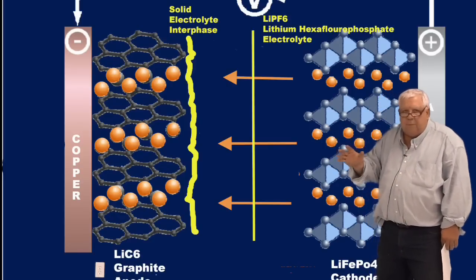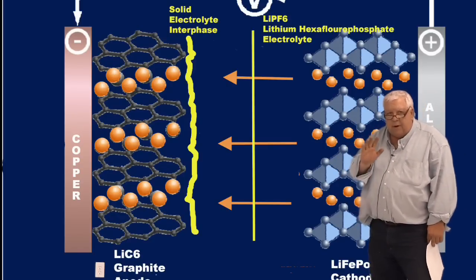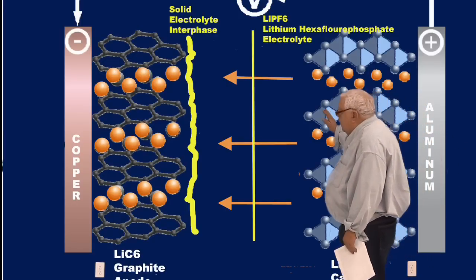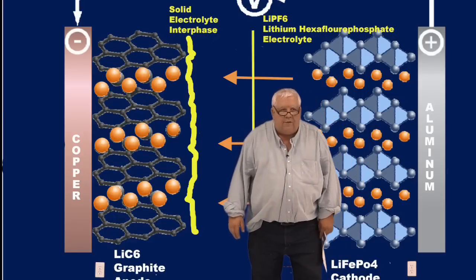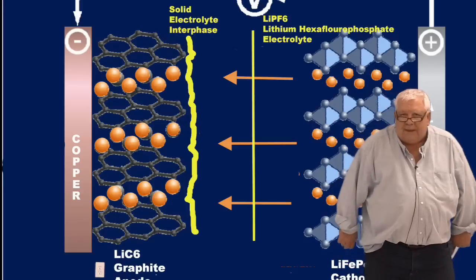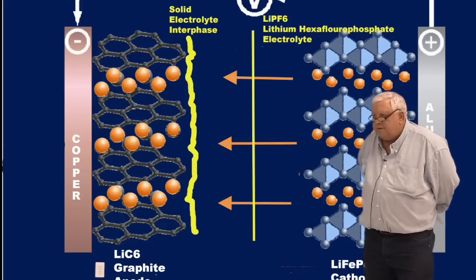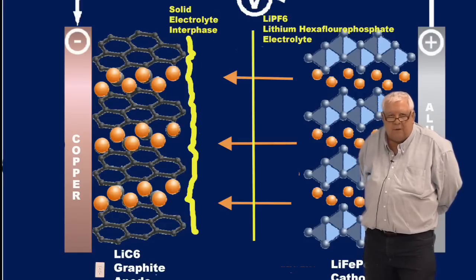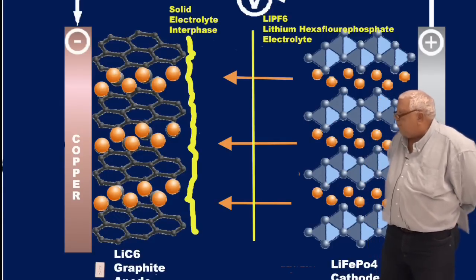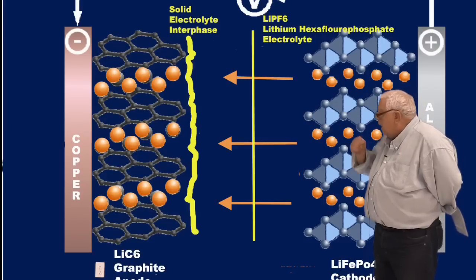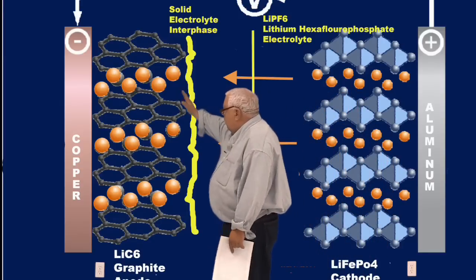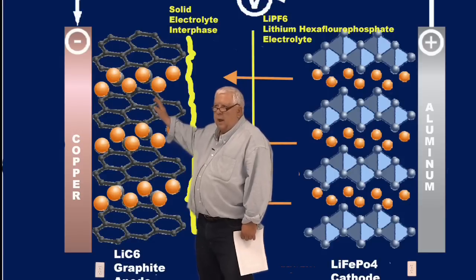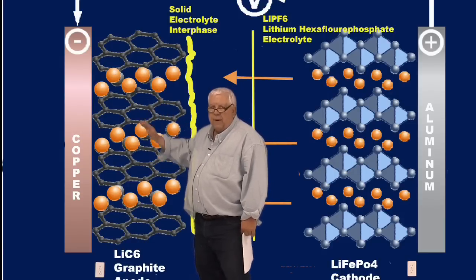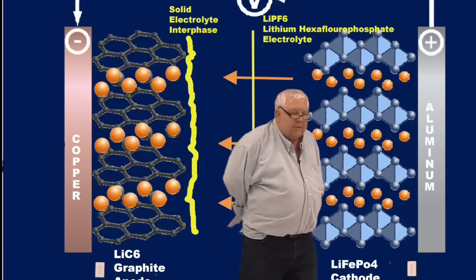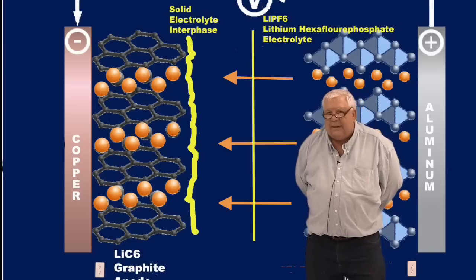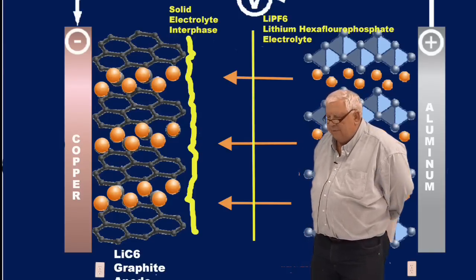In the formative charge of the battery, not only, but primarily in the formative charge of the battery, our lithium ion is trekking across here, and it reacts with these solvents primarily in some bad ways. And that causes the solvents to precipitate some solid matter, some precipitates that come out of the solution and become solids. And they form a thin skin, a kind of vinyl covering or a rubber coating on our carbon anode. And we call this the solid electrolyte interphase layer.